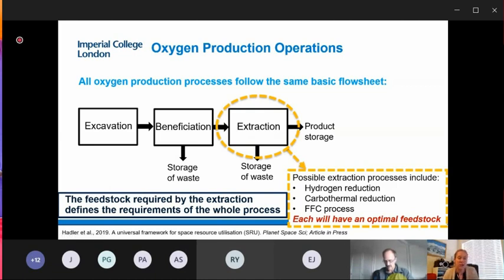each of those will have an optimal feedstock. So what we want to do is work out how we produce that optimal feedstock. Now, the challenge here is that nobody really knows what the optimal feedstock is. All of these people that have looked into hydrogen reduction, carbothermal reduction, electrolysis processes, there's been very little done to say, actually, this is exactly what you want to put into your reactor. You want to put in particles of this size and of this type. And this, we feel, is a big oversight, because that requirement defines the whole process. If we're thinking of a process from excavation through to the production of oxygen, then what we put in the reactor defines how big our excavation system will be. And it really defines the scale of the whole process.